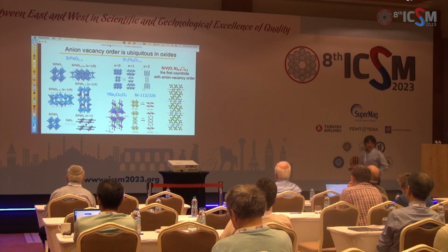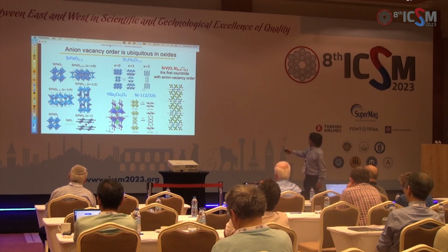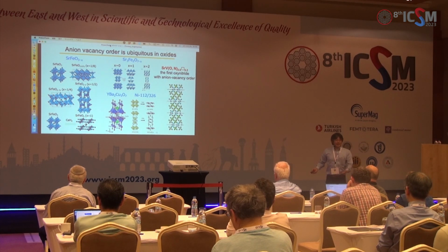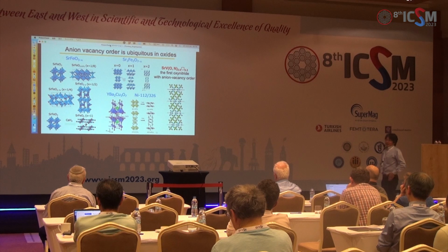So in terms of the oxide, actually the oxygen vacancy order is ubiquitous, as you can see from this material, or maybe YBCO. Actually, YBCO is an oxygen vacancy order structure as well as an A-site order structure. So there is a lot of physics in this oxygen vacancy order. But in the case of oxynitride, there is no example of oxygen vacancy orders. So this is the first example of this type of structure.